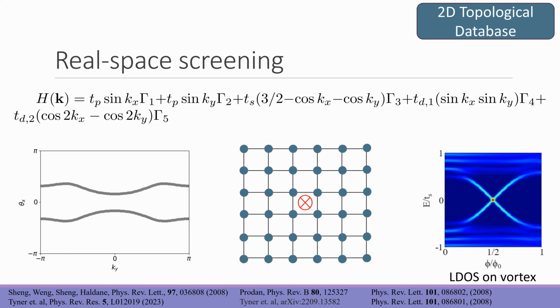Let's modify our spin Hall insulating model by including these extra d-wave terms that I've added. This band structure still has PT symmetry, still one Kramers degenerate valence band and one Kramers degenerate conduction band. But by adding these additional terms, I've trivialized my Z2 index. We could tell this by looking at inversion eigenvalues, and also by looking at the Wannier center charge spectra and seeing that it's gapped. This falls under the category of what's known as a higher order insulator. It has gapped surfaces, but it has these corner-localized modes.